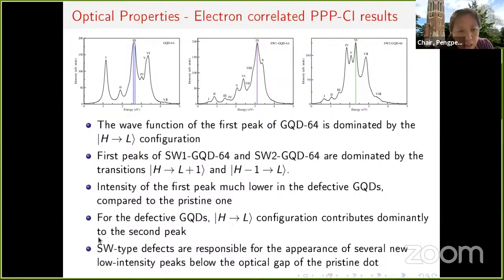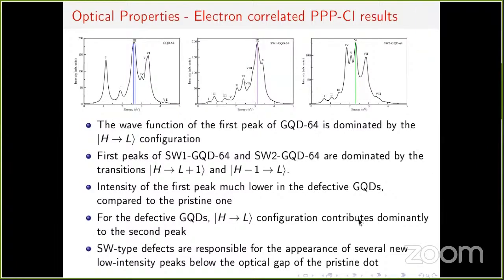Okay. For the defective quantum dots, the HOMO-LUMO configuration contributes dominantly to the second peak, and we have a major oscillator strength redistribution, as you can see. Many peaks now appear in the low energy region for the defective quantum dots.